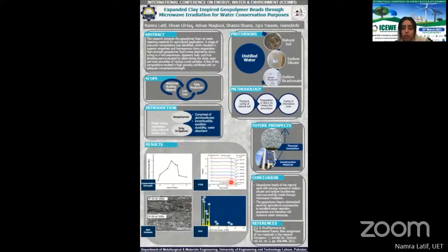The water solubility test and water tension test results exhibited that a few of the compositions were entirely water insoluble due to aluminosilicate linkage and could store water in a reasonable ratio. The results justify geopolymer foams as potential candidates for water retention in agricultural applications.